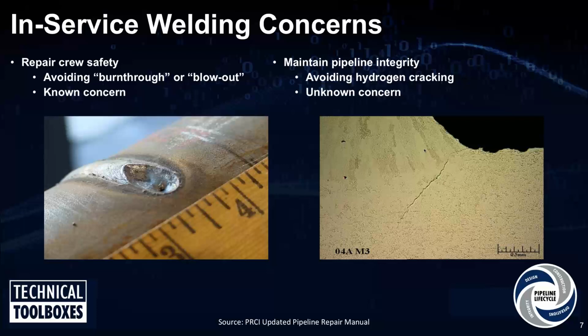Yeah, you can inspect these welds. Your inspection might come back clean and you think that you're fine, but in reality, there's a lot of shortcomings to the inspection methods of in-service welds. And it's not so much the inspector or the inspecting technique, it's really just the physics of the inspection method that makes these types of welds difficult to inspect. So you might do an inspection, think your weld's clean, but you might still have cracks because of that unknown aspect of hydrogen cracking. That's why I tend to think it's a little more of a concern.